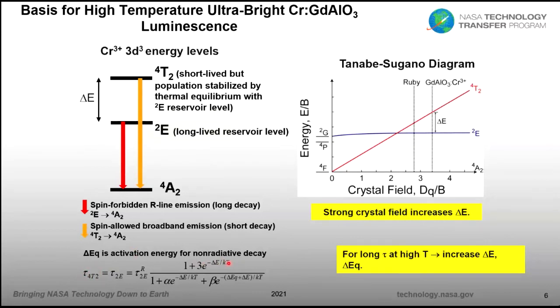Now, to have good high temperature measurements, you don't want your decay time to become too short. So for this to remain long, you want your delta E and delta EQ to be as big as possible. Delta E is simply the energy difference between these two excited levels, and delta EQ is an activation energy for non-radiative decay. If you look at what's called a Tanabe-Sugano diagram, it shows that as you go to materials with higher and higher crystal fields at the dopant location, this gives you a larger and larger delta E, which is what we're looking for. That led us to the selection of our chromium-doped gadolinium aluminate and some of the other aluminates, because this material gives you the highest delta E you can really find. It's even larger than what's seen for ruby, which is already considered to have a high crystal field.